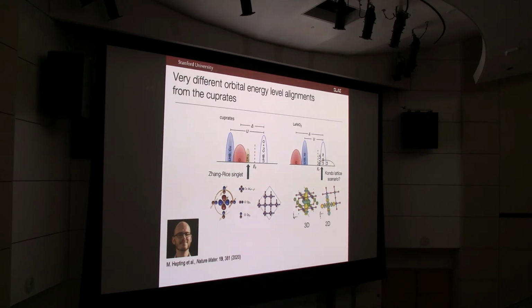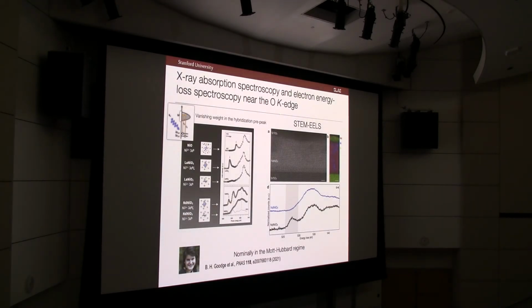So some of the things that spectroscopically give the backbones of this picture, I'll show you here, for example, the oxygen K edge. So X-ray in and looking at the absorption associated with these transitions, looking at, say, nickel 2+, the perovskite nickel 3+, or the infinite layer phase. In these two earlier cases, you see this strong hybridization pre-peak preceding the oxygen K edge. But both in lanthanum nickel O2 and neodymium nickel O2, this is vanishingly small in the case of the d9 electron configuration.